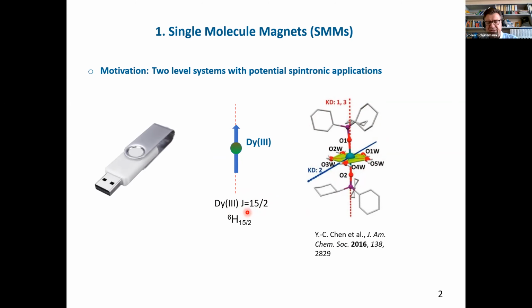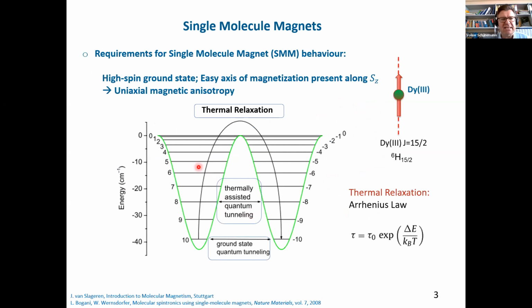And that motivated us to start dysprosium-161 NFS and also NES. The requirements for single molecule magnets are a high spin ground state and an easy axis of magnetization along Sz. So it should have a uniaxial magnetic anisotropy, but it can have thermal relaxation, so the magnetic moment can relax in that way. But it can also be thermally assisted quantum tunneling through the quantum barrier. And it can also have ground state quantum tunneling. That's the reason that these systems don't exist with hysteresis at room temperature yet.